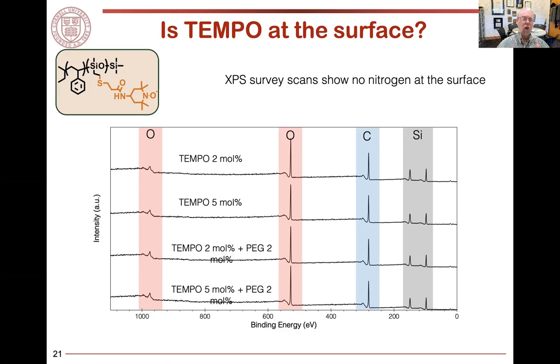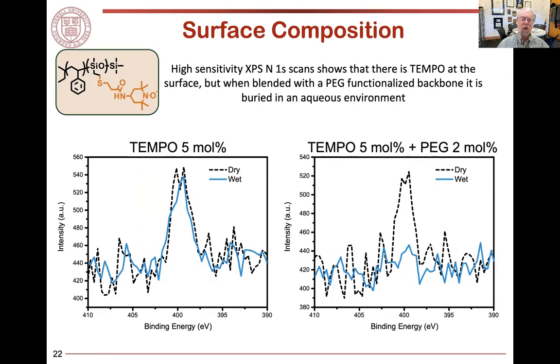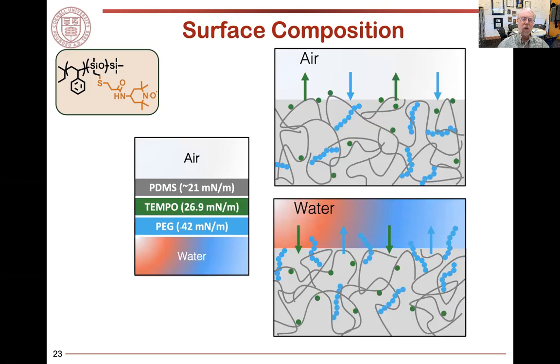And so in the coating process, the PDMS and the TEMPO are competing for that low energy surface, and the PDMS always wins. And so it becomes buried. You don't see the nitrogen that's characteristic of this structure in the final material. And if you zoom in, you can also see that if you incorporate PEG as an additional component in a second block copolymer, in the presence of water, the PEG goes to the surface. And so in neither situation does the TEMPO win out. And so we have to be more sophisticated in the way we design these components.